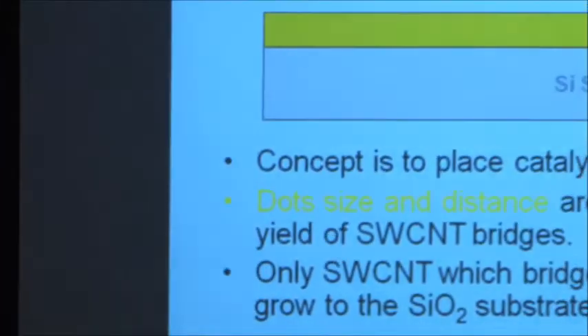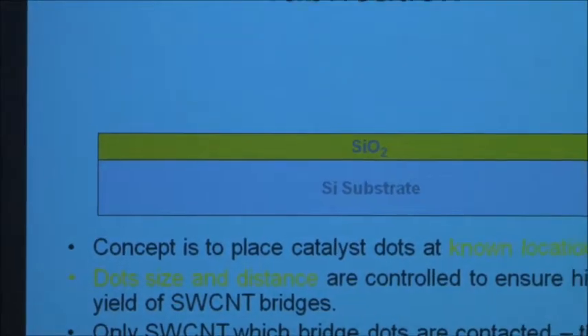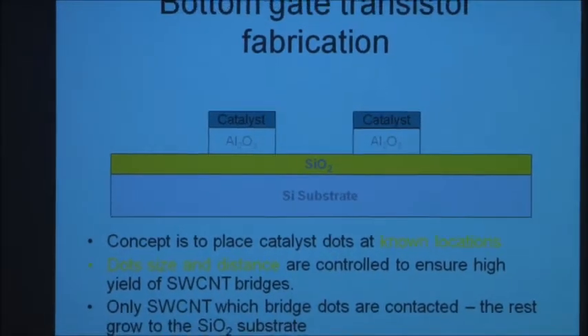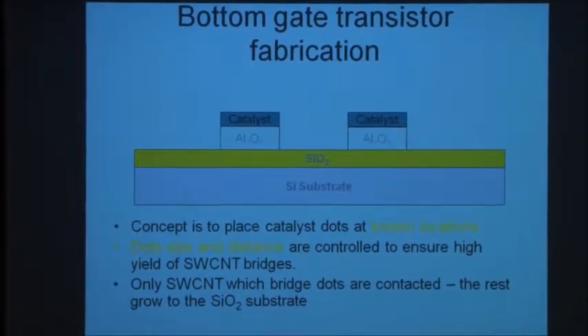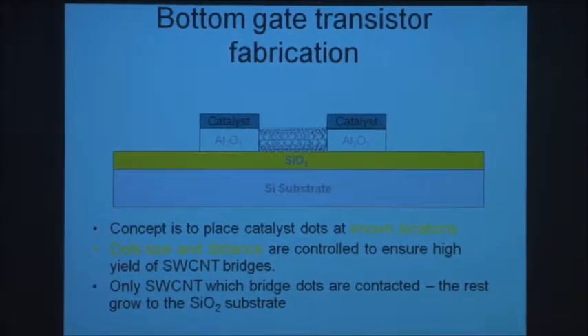So here what you do is you start off with a bottom gate transistor, which is like using silicon as the back gate, highly doped silicon. You put down SiO2. Then you put down some catalyst, usually with a barrier layer of Al2O3, and you grow a nanotube between them.